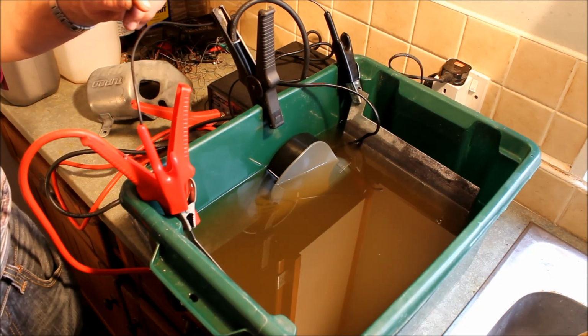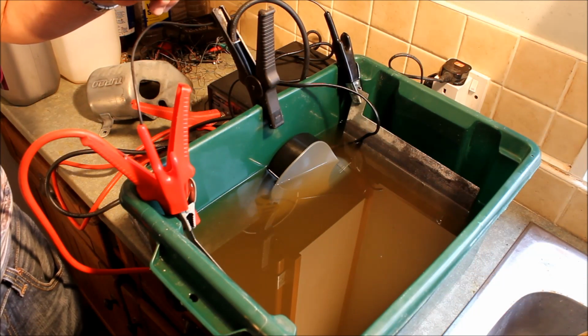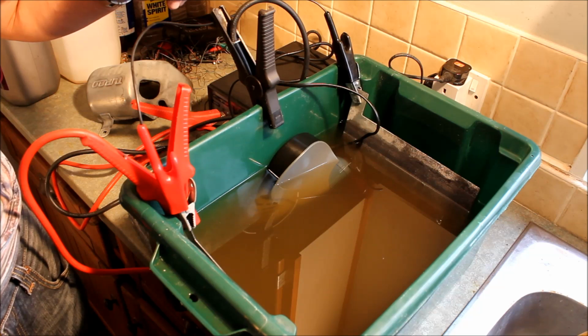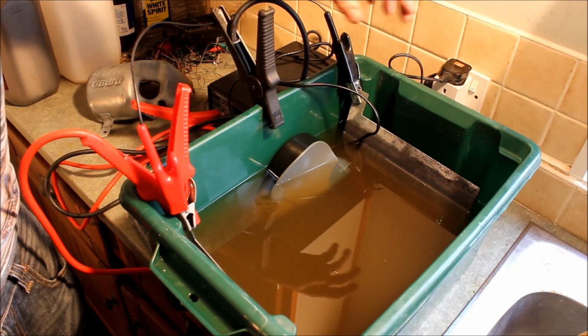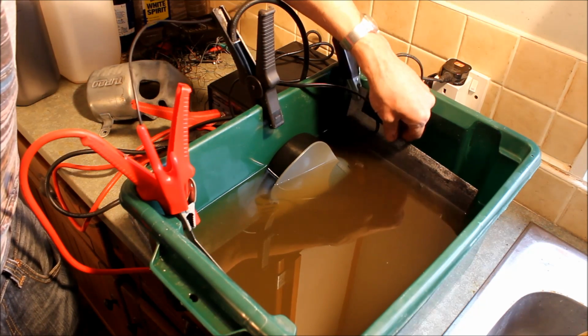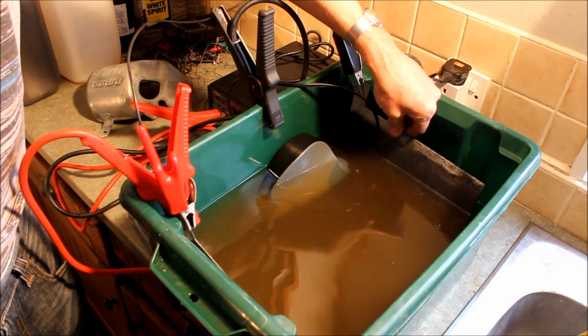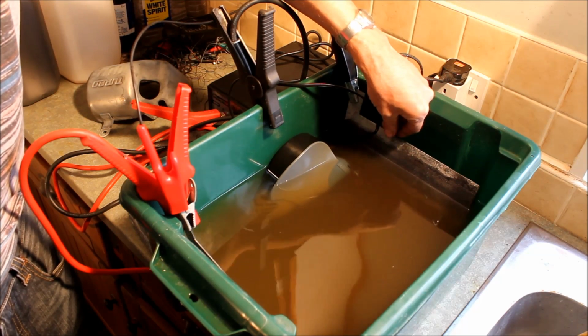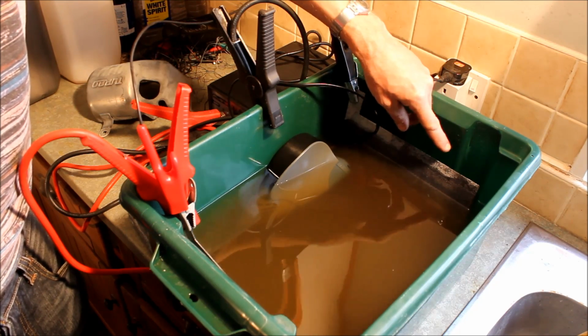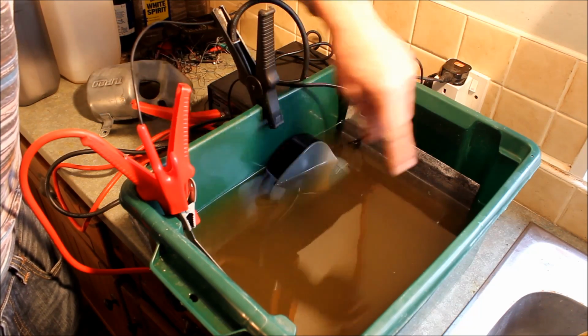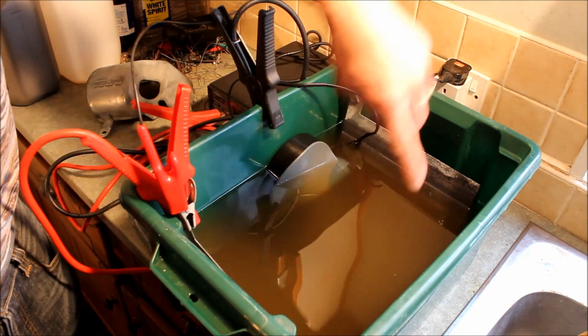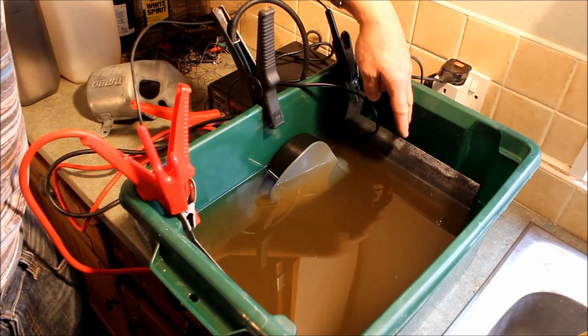If you're having problems with burning and high or uneven current densities, then here's a couple of things to try that might help you out. Firstly, anode area. Make sure that you have at least as much anode area, and preferably twice as much anode area as the thing that you're trying to plate, and space those anodes out around the tank so that you're getting as even a coverage as possible.